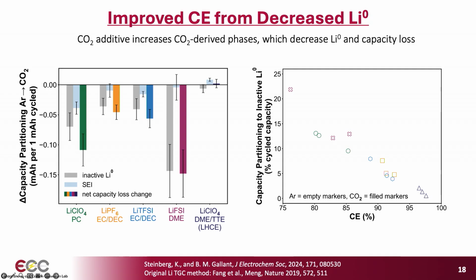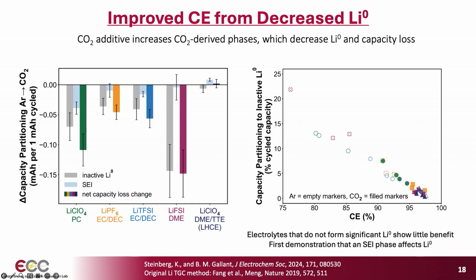The exception is this one here, where there really wasn't much dead lithium to start with, so we didn't see much change. And so this graph really brings it all together. This graphs the capacity loss partitioning to dead lithium as a function of Coulombic efficiency. And you see this kind of universal trend line where increasing Coulombic efficiency requires decreasing the dead lithium in the sample. So what happens when we add CO2, we're basically moving down and to the right. But the physics governing the system are really the same physics. And so this was very fascinating to see.